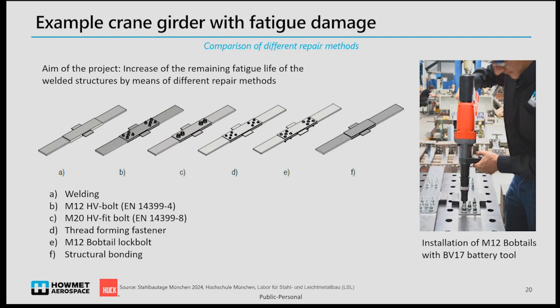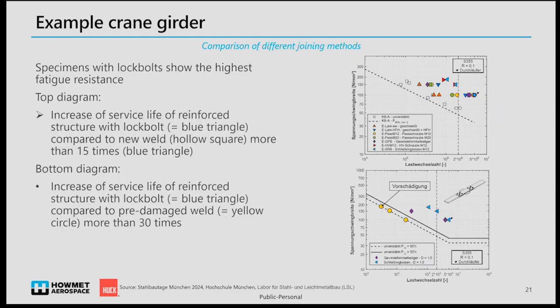these specimens were then loaded into a test machine. And on the right-hand side, we see the results from these comparative tests. In the first diagram, the white squares show the original welded structure in the original design without any damage, so it was basically newly welded, compared to the 5 other mentioned joining methods. The blue triangles show the results for the lockbolt, and we see the highest fatigue resistance with our lockbolts compared to the other joining methods.